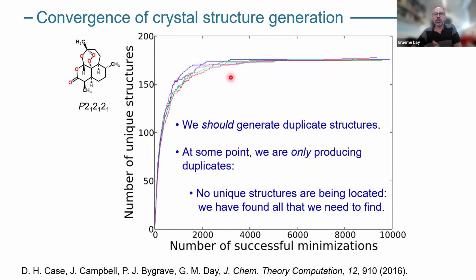We want that to happen. We should generate duplicates because that's telling us that we're getting to a point where we're sampling the energy surface with enough density of points that we're finding all of our local minima. So that gives us confidence in the search. And at some point along here, we are only producing duplicates, and that tells us it's probably safe to stop. There are no new unique structures being found, and so we say that the search has converged. What you see is in a single space group for a small rigid molecule, that's happening at many thousands of minimizations. So if I want to look at a range of space groups, then I'm going to need many, many thousands of energy minimizations.